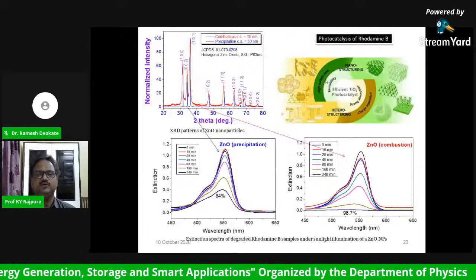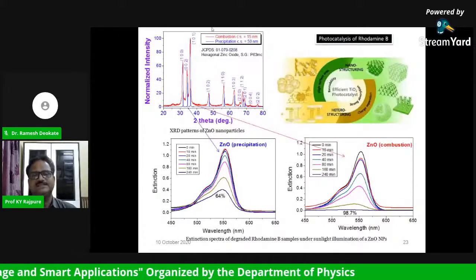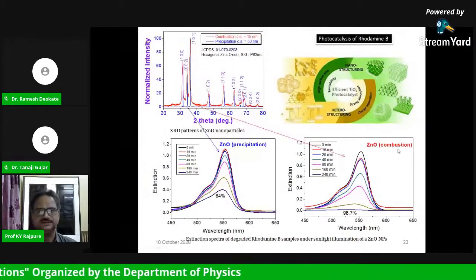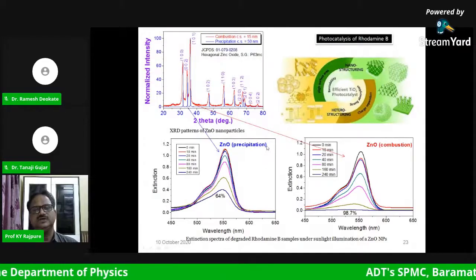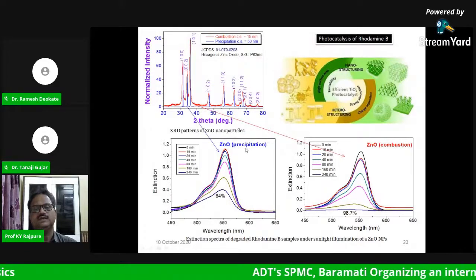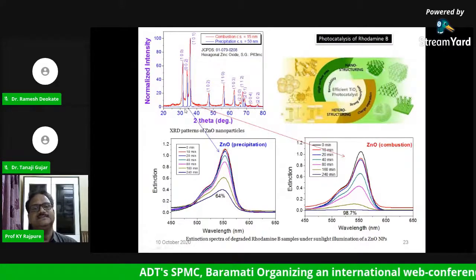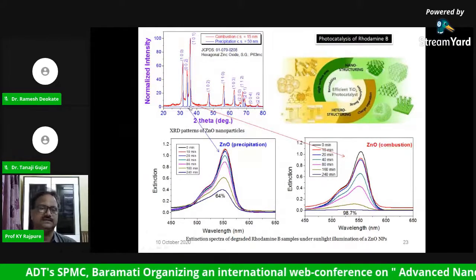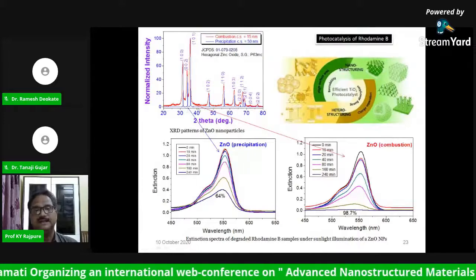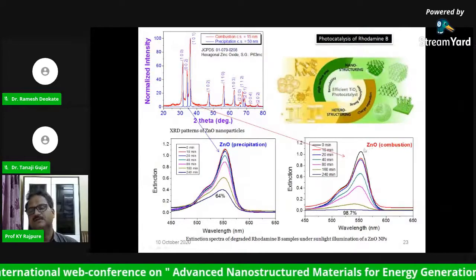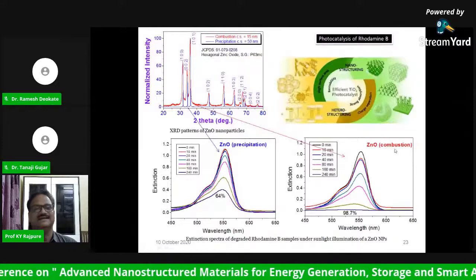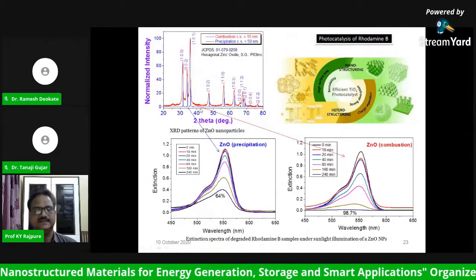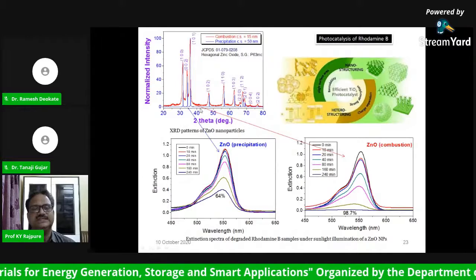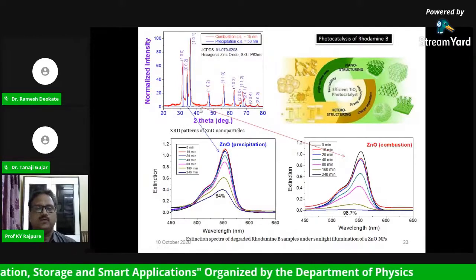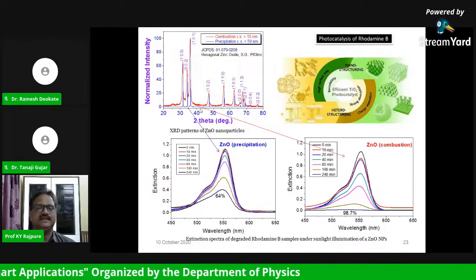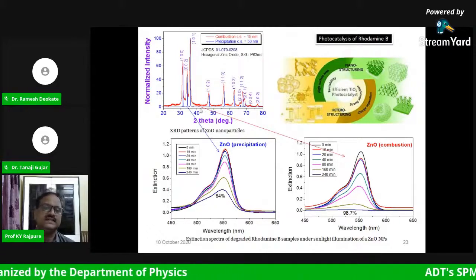Therefore, we prepared zinc oxide via two chemical routes, precipitation and combustion. It was observed that the zinc oxide prepared by the precipitation route and subsequently sintered exhibited a polycrystalline nature, or the crystallinity was more. But the powder prepared with the combustion technique exhibited a nanocrystalline structure. The theme of this conference is the use of nanocrystalline material. What is the advantage of nanocrystalline material in photocatalysis? I am going to address that issue, but later on.